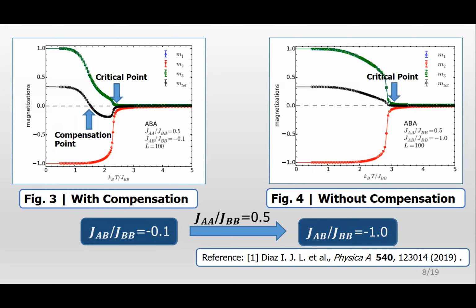We understand that compensation is basically a bulk phenomenon, and because of non-zero interlayer antiferromagnetic coupling, the bulk and individual layers both have actually the same critical temperature.